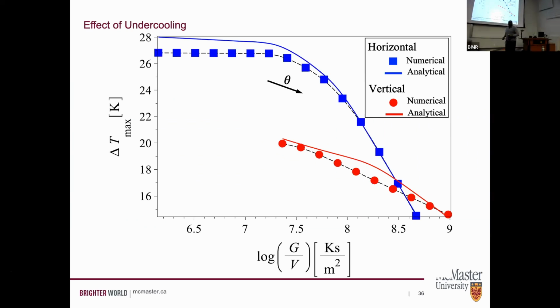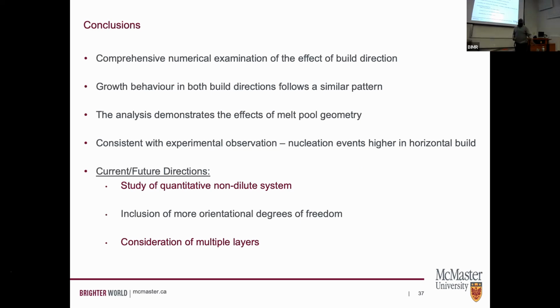And so at the end of the day, in terms of horizontal and vertical, because the two different directions see different undercooling ahead of that growing solid, we should expect that they have different microstructures. And so the quick recap: there we saw different behavior as a function of the growth direction, all dictated by undercooling, dictated by nucleation. And this, at least we think, is consistent with what has also been observed in experiments.